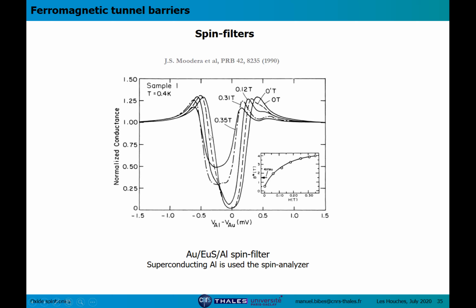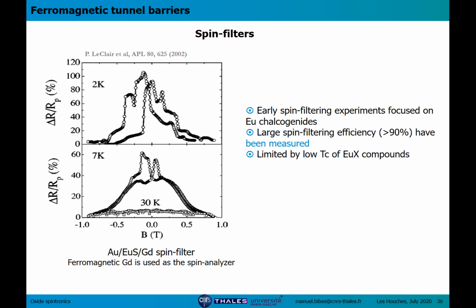So you can see from this curve that for some magnetic field, you recognize the four-peak structure that we had when we were tunneling from a spin polarized ferromagnet. But mostly you just have two peaks. Why do you have two peaks? That's because the spin polarization is extremely high. It's around 90%, so the peaks corresponding to spin down are almost completely washed out. So from this data, one can extract a spin polarization value of about 90%.